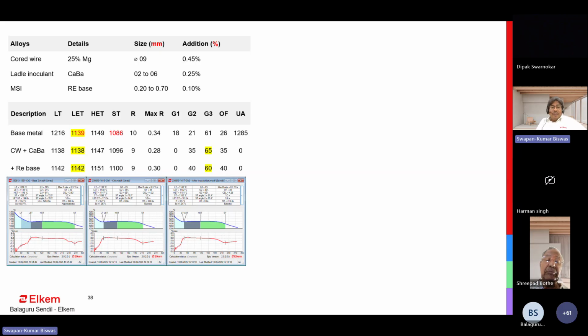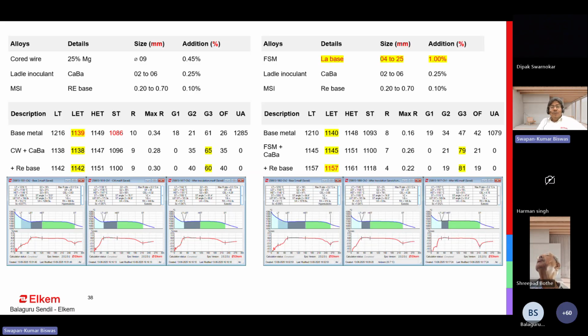So when our team, especially Balaguru and other team members, visited, they did this thermal analysis with the existing combination and with the new combination, this ferrosilicon sandwich process with lanthanum-based ferrosilicon magnesium. In this picture, you will get the idea. Normally, in the case of ductile iron, G3, the green portion, is the last graphite precipitation. If it is on the higher side, you will get more nodule count and the effect will be almost negligible. So when they are producing castings through cored wire, G3 is around 60 to 65%.